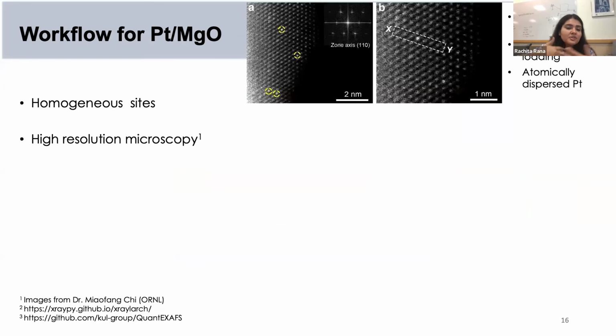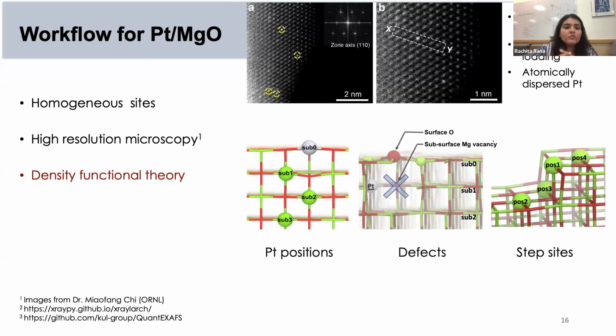So the first thing was once the material was synthesized, this was done by Bruce Gates's postdoc then. The idea was to characterize this to see how homogeneous the material was, and we did high resolution microscopy at Oak Ridge to get these images. And then once we had confirmed that this is a very homogeneous platinum on magnesium oxide system, there were no metallic clusters or anything, we wanted to then start doing density functional theory calculations.